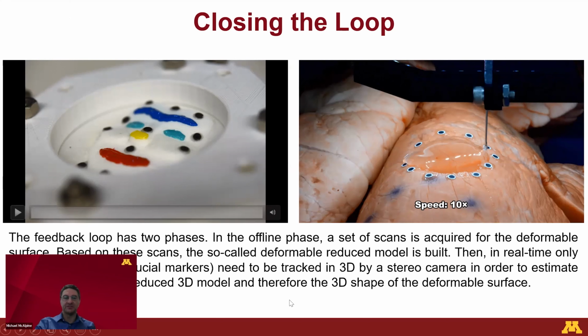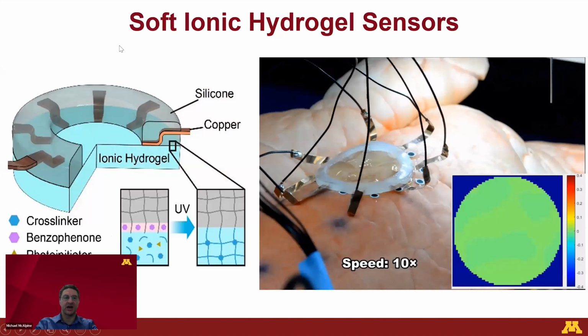Of course, you have to cure it first, but once you do, you are creating this ionic hydrogel-based device. You cure that ionic hydrogel under UV, and then you place some electrodes around the circumference of it, and this creates a type of device called an electrical impedance tomography device. Even though it's a uniform ionic hydrogel, by placing electrodes around the circumference, sourcing current and measuring the voltage continuously, you are creating a pseudo array of sensors on the device, even though you're not actually dividing the device into arrays of sensors. And that's the beauty of the tomography system.